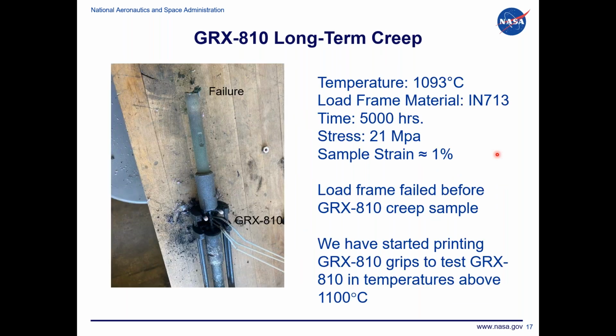So it's a pretty phenomenal result here. I really like to show this picture. We wanted to do a very long creep test for GRX-810 at 3 KSI, so 21 megapascals, with the new M280 material. But we had an issue, because in this test, after 5,000 hours, having reached about 1% creep strain, the sample failed. And it was kind of disappointing because it was sooner than what we were hoping for. But when we opened up the furnace, what ended up failing wasn't the GRX-810 sample. It was actually the load rod that it was attached to. And so I think this just helps prove the point that this GRX-810 material is significantly better than a lot of these conventional superalloys. In fact, as we're trying to do these much more elevated temperature tests of GRX-810, we've actually had to start printing our own test fixtures out of GRX-810 to be able to test it.